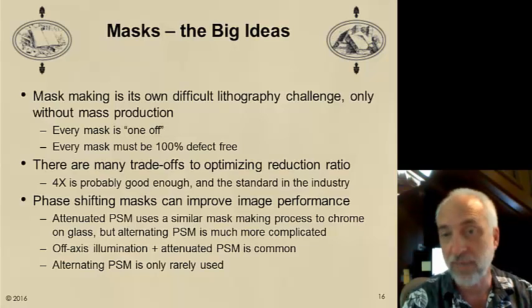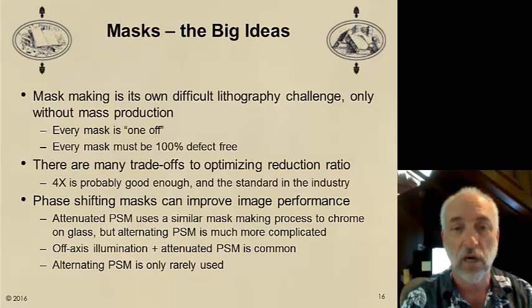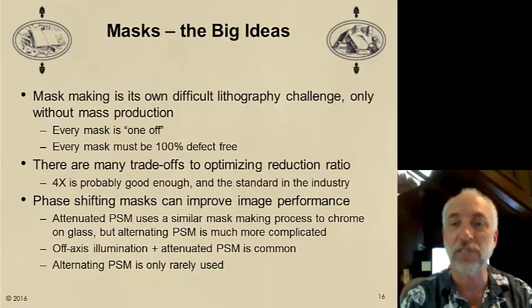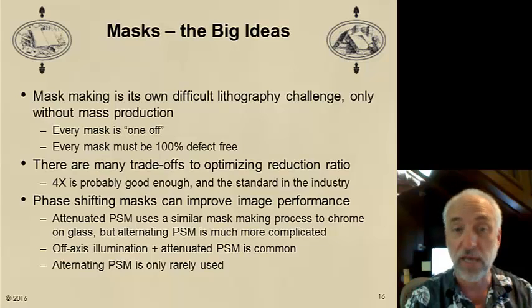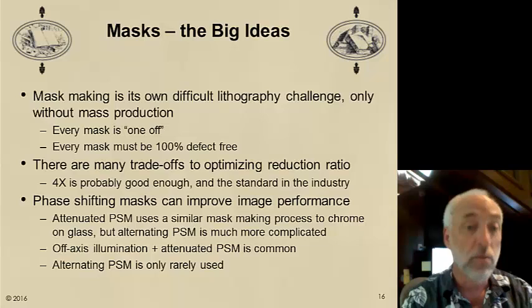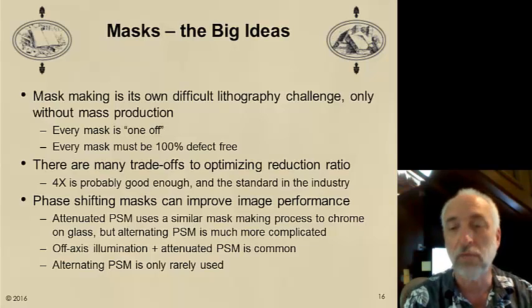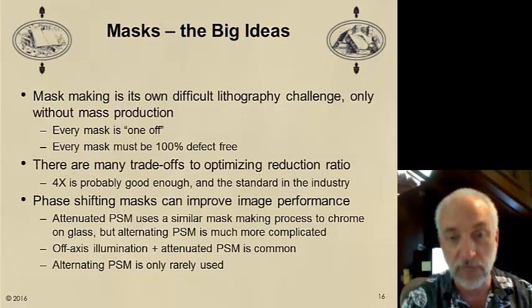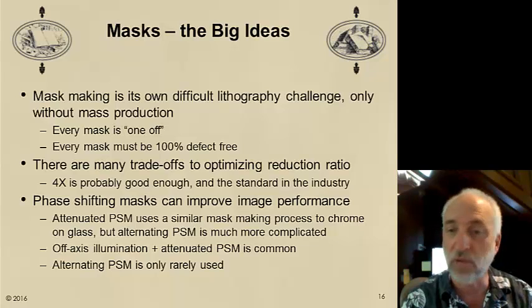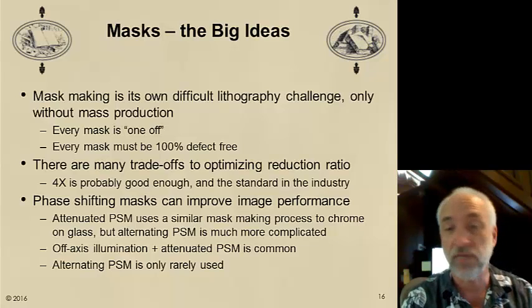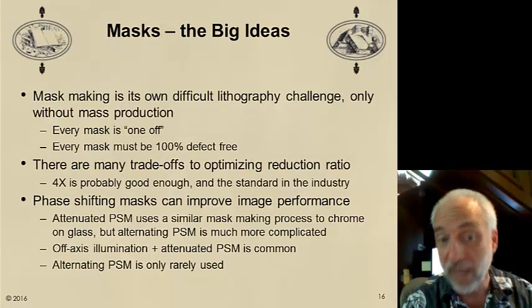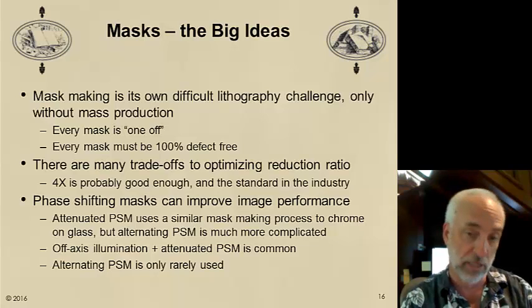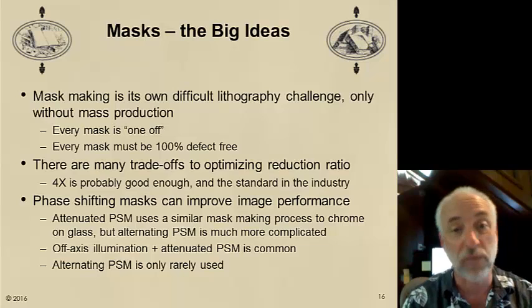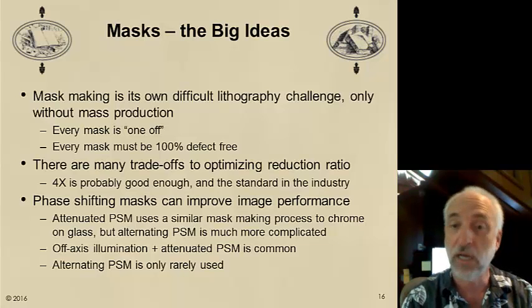We talked about the trade-offs to optimizing the reduction ratio and found that the 4x, whether it's the exact optimum or not, it's good enough and it's the industry standard. Combine that with a 6-inch plate and we have the way masks are used in semiconductor manufacturing today. Finally, we talked a little bit about phase shifting masks and how phase shifting masks can be used to improve image performance. But we learned that alternating phase shifting masks require a much more complicated mask making process than attenuated phase shifting masks. The attenuated phase shifting mask uses a very similar process to chrome on glass. In fact, the attenuated phase shifting mask with off-axis illumination is quite common, and alternating phase shifting masks are used only rarely. In the next couple of lectures, we'll learn a little bit more about mask making, inspection, repair, and a few other topics as well.